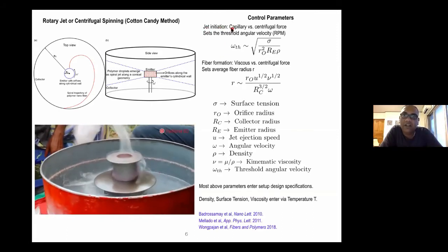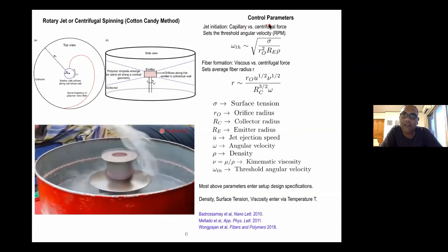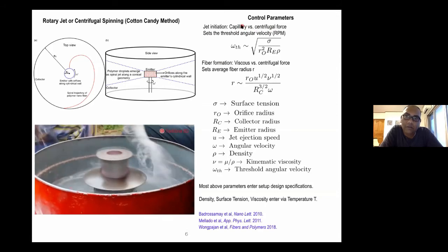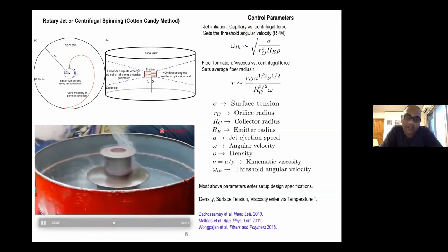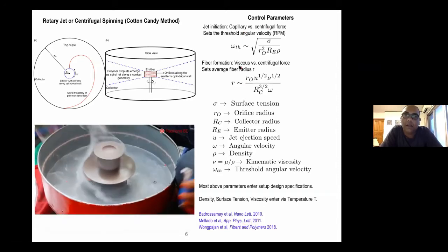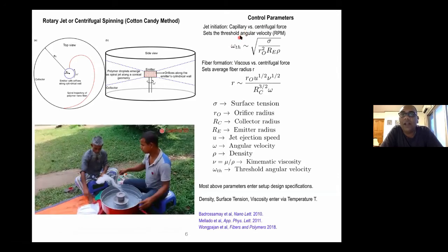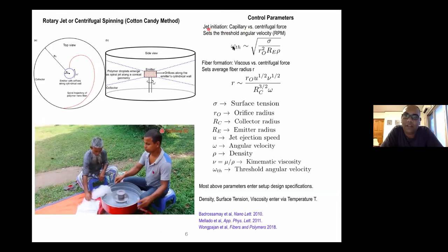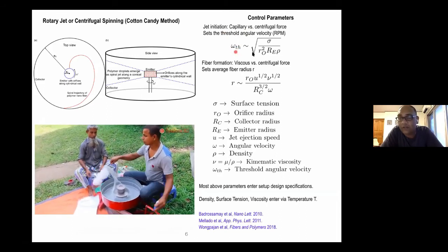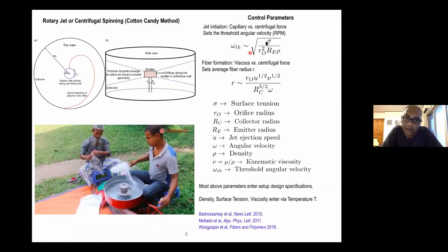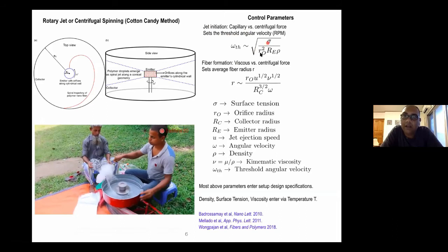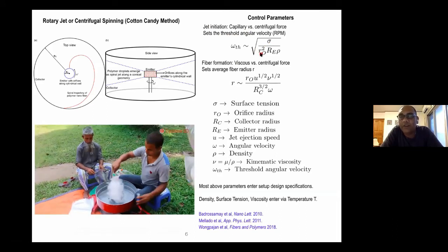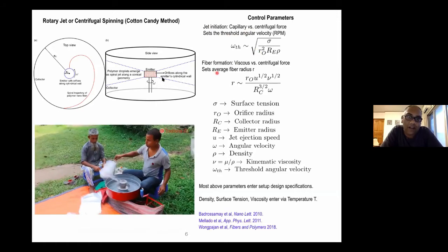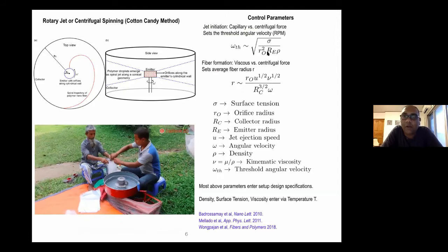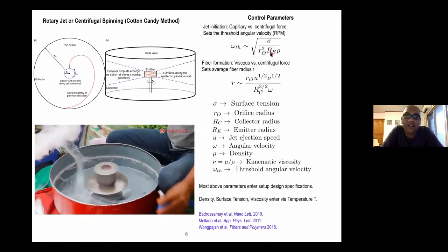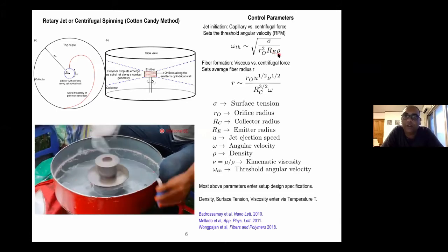In the first stage, you are initiating the jet, where the capillary force is competing with the centrifugal force. When you balance the two, and I'm not giving you the calculation here, it is in the paper that I have referenced below, you get a threshold angular velocity at which the jet can be initiated. The threshold angular velocity goes as the square root of sigma, which is the surface tension of your liquid, divided by R0 squared. R subscript 0 is the orifice radius, the radius of the tiny holes on the emitter wall. Capital R sub E is the emitter radius, and rho is the density of your polymeric solution.